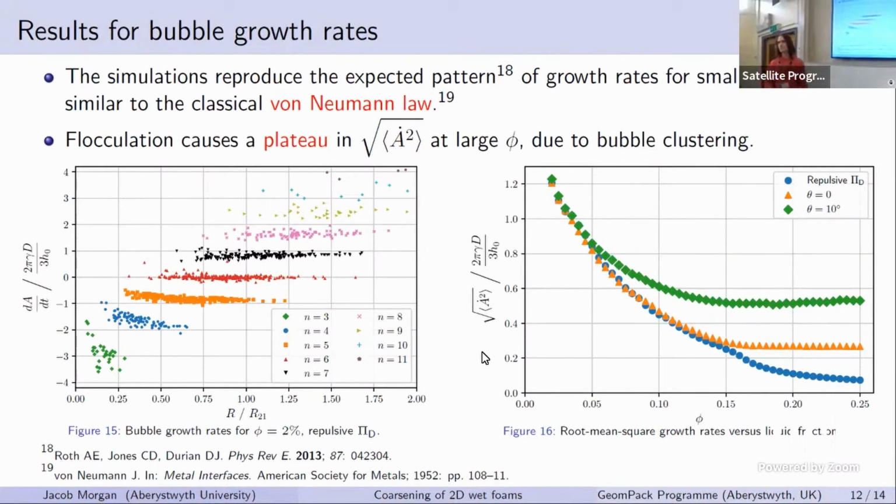Do you get brittle fracture irrespective of contact angle? We haven't looked at that. I wouldn't be able to definitely classify what's occurring, but qualitatively, it appears that small contact angles give rise to a ductile fracture where you have chains of bubbles, whereas you get these big tears, what might be a brittle fracture, at higher contact angles, which interestingly, coincidentally occurs at about 10 degrees, present at the 10-degree contact angle which we consider. A 3-degree curve would look like something intermediate, or